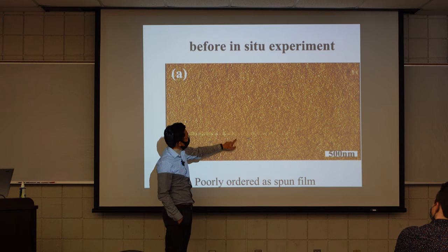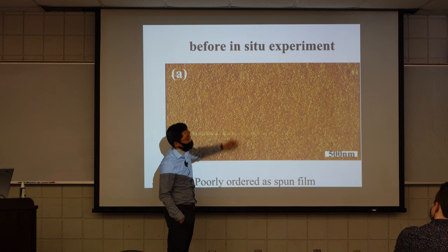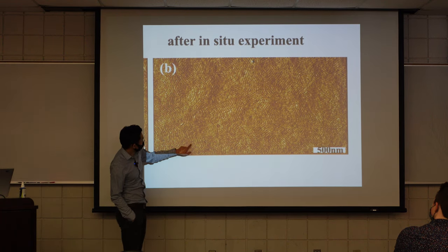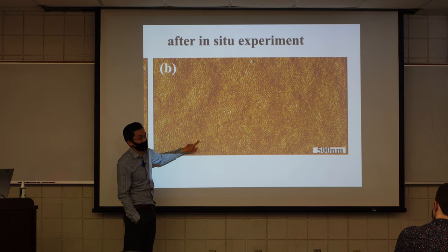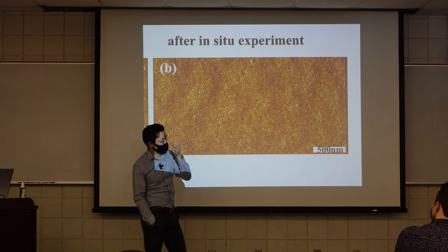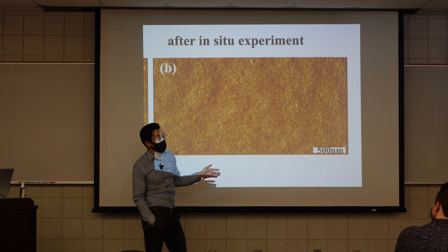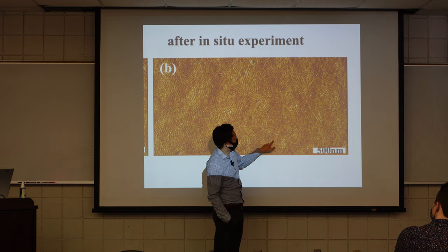This may be a little bit hard to see down there, but before we anneal them, they phase separate but pretty poorly ordered. You might see a few lines here and there, but only short-range order. But after we do that annealing for about 70 minutes, you start to see quite obviously those cylinders, or potentially vertical cylindrical lamellae, either is possible. But in this case, it's actually a cylindrical domain defined by 30% volume fraction of the minor block, PVP. So these are cylinders lying and going through this fingerprint pattern.